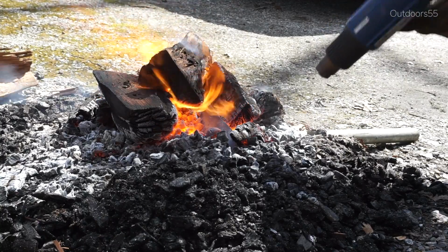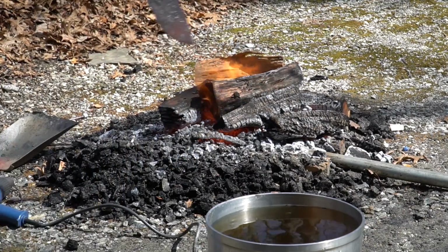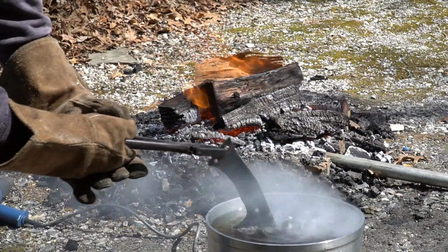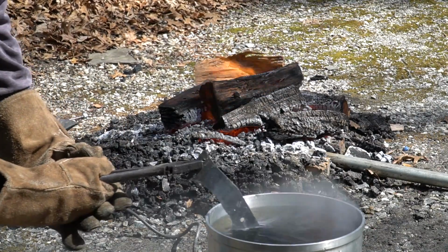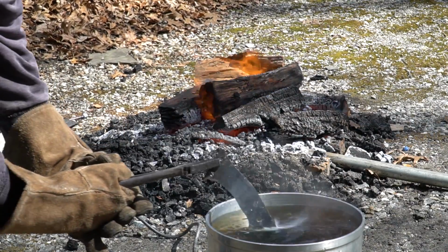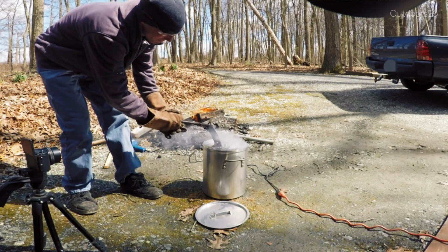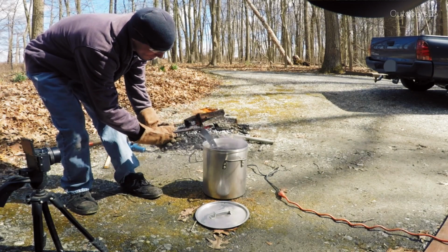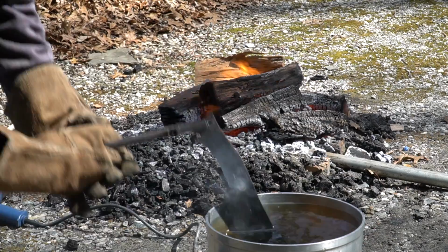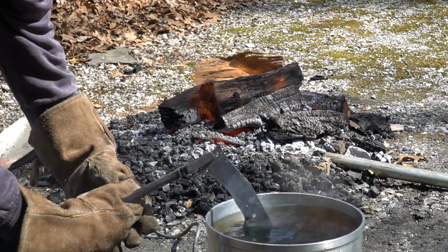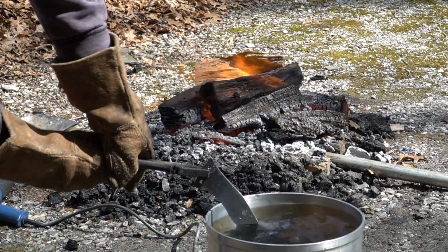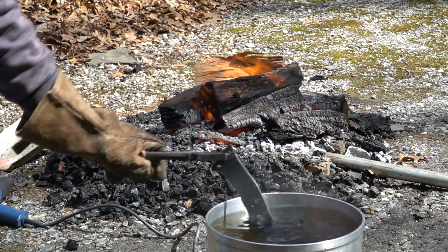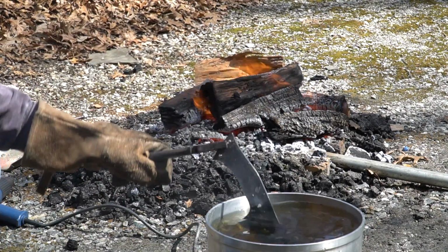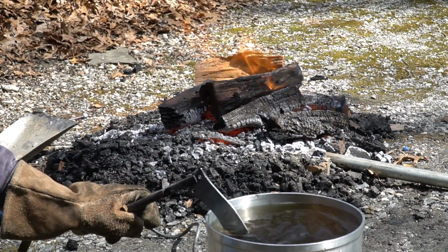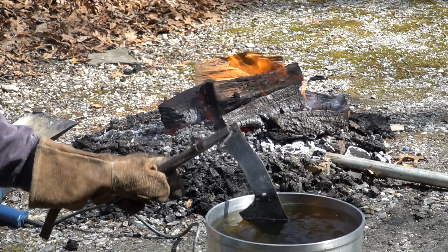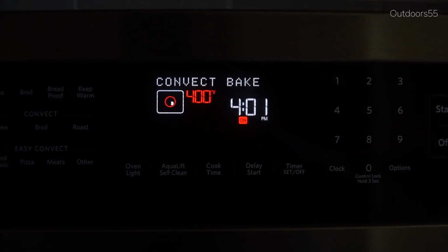So when you go ahead and do the quench, it's best to quench straight down as quickly as possible. Try not to hit the bottom of the oil pan like I did here, but quench as quickly as possible, and also agitate the blade in the oil. Don't use a swirling or stirring motion. You want to kind of rock the blade back and forth, kind of slicing into the oil, and that will help cool the steel as quickly as possible. Once a knife stops smoking when you pull it out of the oil, you can simply take it out and let it cool to around 125 degrees or so.